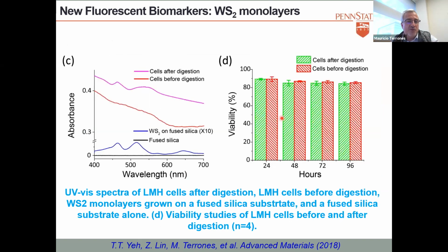This is just to show you the absorption. So you have the cells before digestion, right? These two peaks are the A and B excitons of the tungsten disulfide. This is the fused silica. After digestion of the cell, you see these two peaks in the cell. So that means the cells have ingested the material.